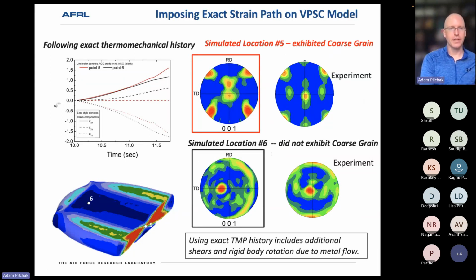Next, I want to just show 2 quick points from the uncoupled VPSC model. So I went to the very center point here, number 5, and then we also looked at my favorite point, number 6, which did not show any of the abnormal grain growth. And so we used the exact thermomechanical history from the finite element simulation to drive the VPSC code. So we were updating the incremental strain rates as the simulation proceeded. As the strain path would change, the VPSC code would respond. And again, we were adjusting primary alpha volume fraction and strain partitioning as well.